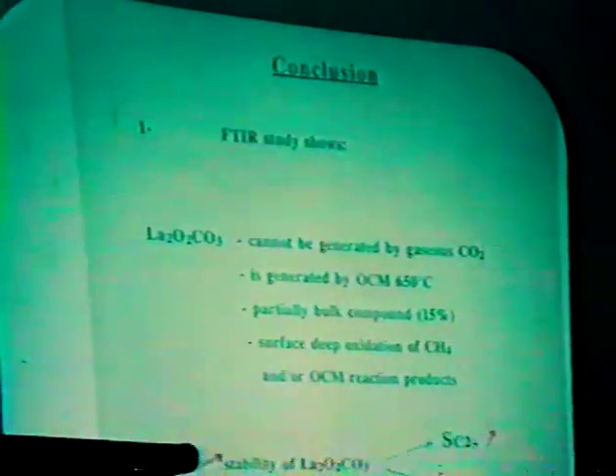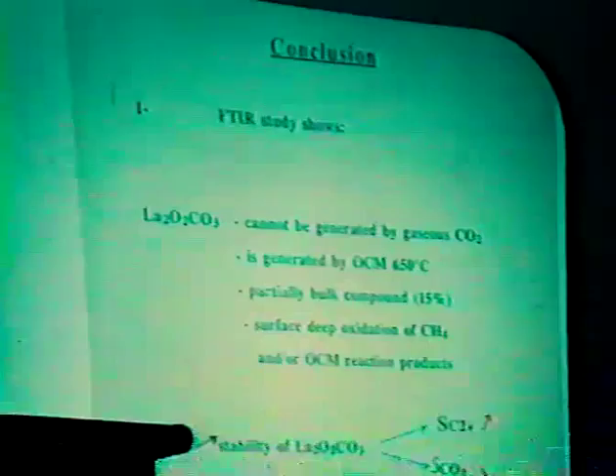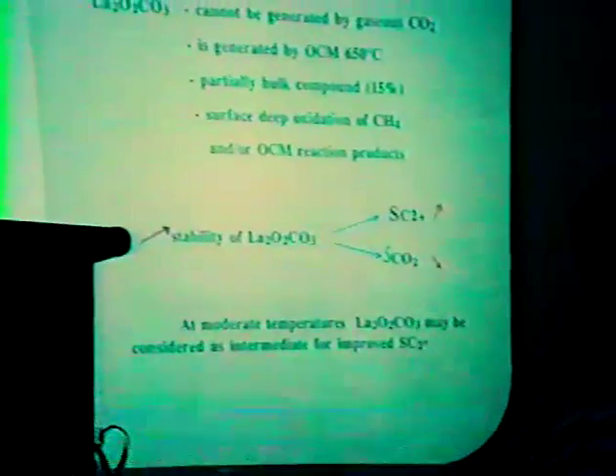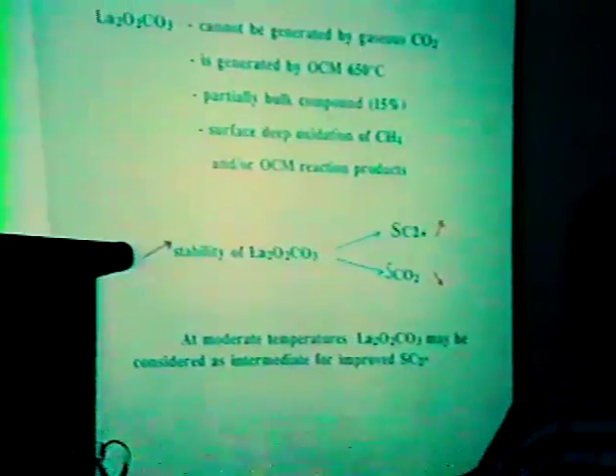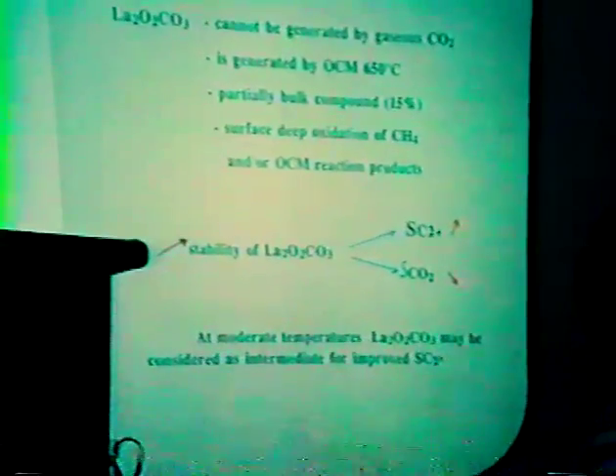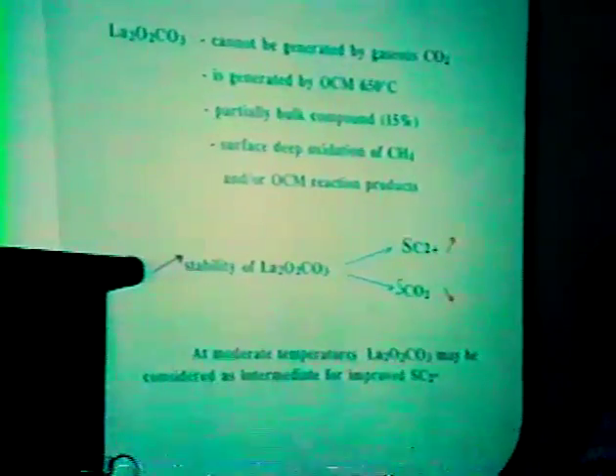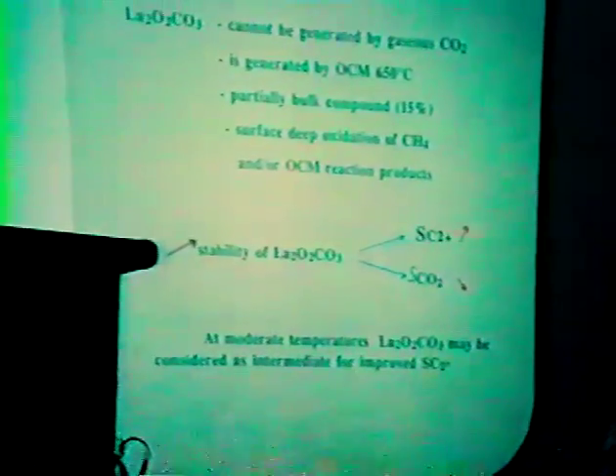To conclude this study, we have shown that the oxycarbonate at moderate temperature is not generated by the CO2 produced in the gas phase by the oxidative coupling of methane. In this view, we can say that the catalyst doesn't act only as a spectator, but is fully involved in the production of CO2 and the C2+ reactivity.